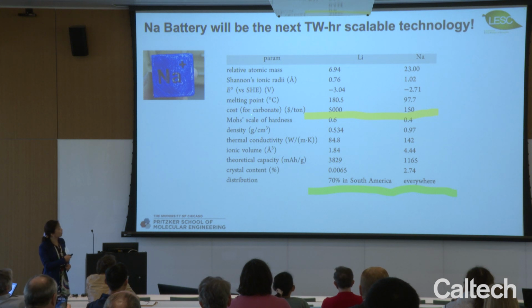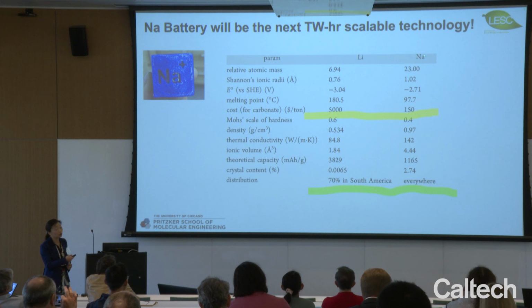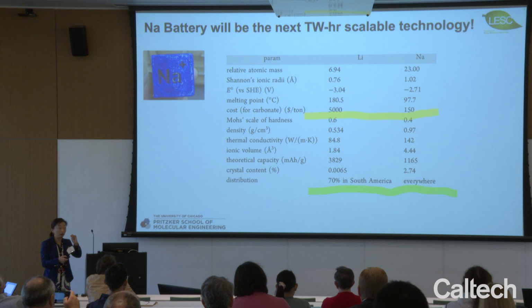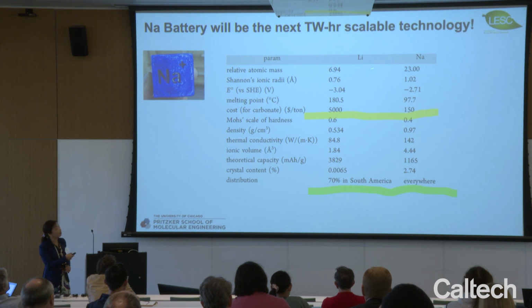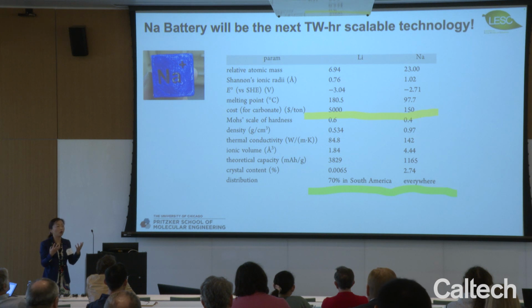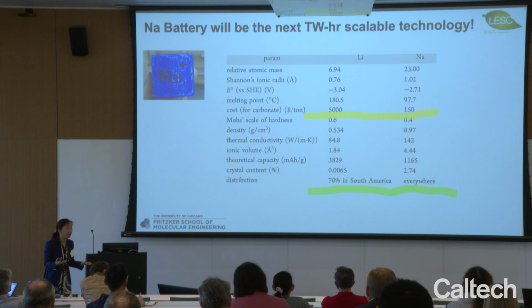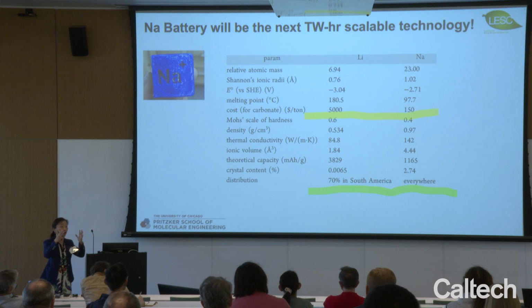If you look at the electrochemical standard potential, most of the sodium analogs of the lithium compounds have slightly lower voltage, about 300 milli-electron volt differences in the voltage. So the downside is, of course, the relative mass for sodium is big. So a lot of people in the early days just thought, oh, volumetric energy density, sodium has no way to compete with lithium because per volume you can only store less sodium because of the size.